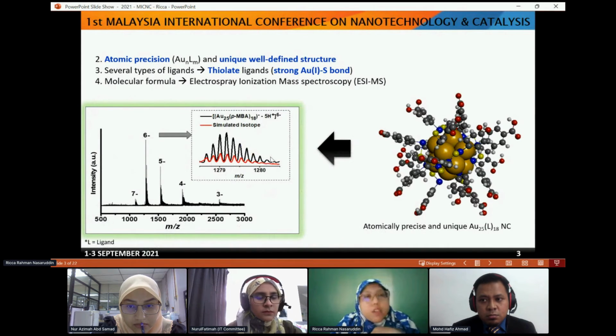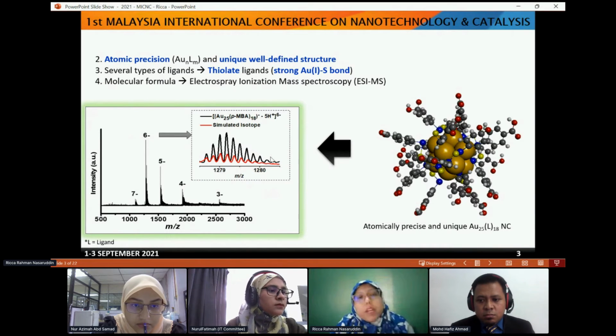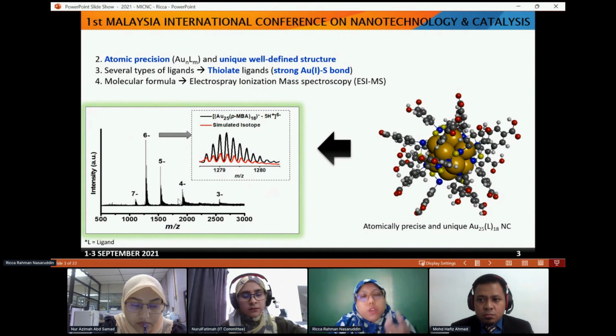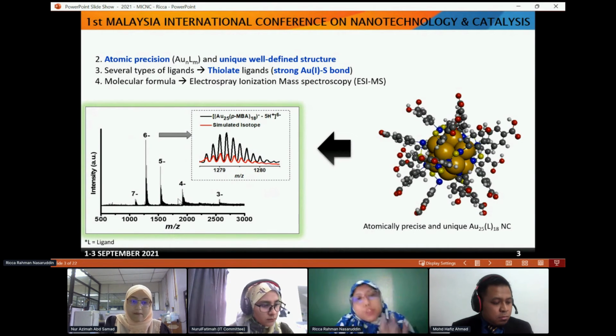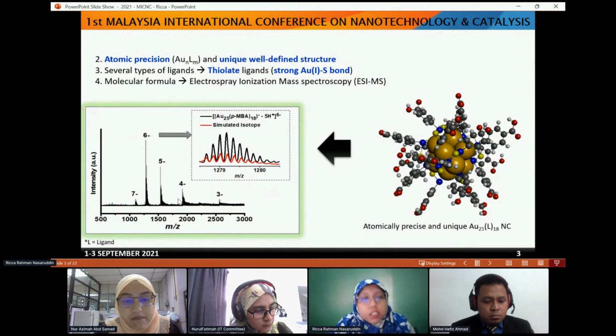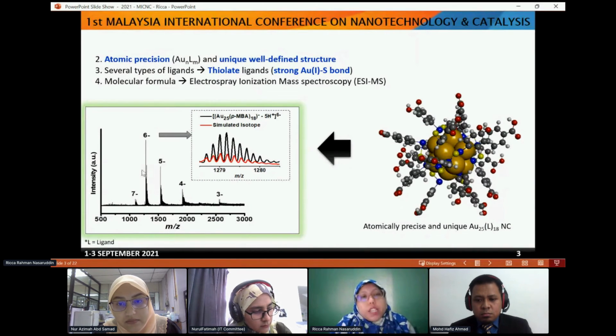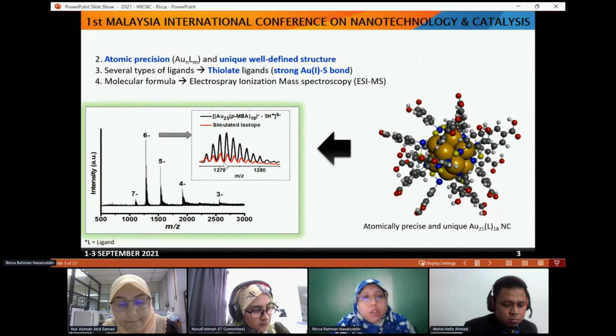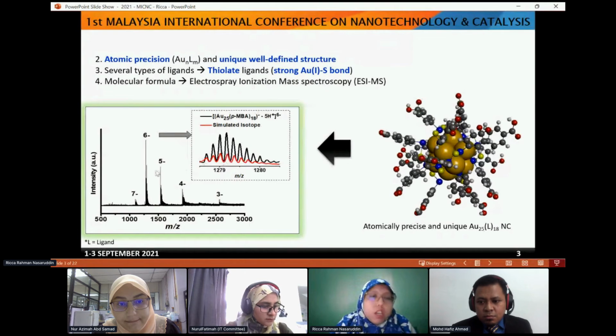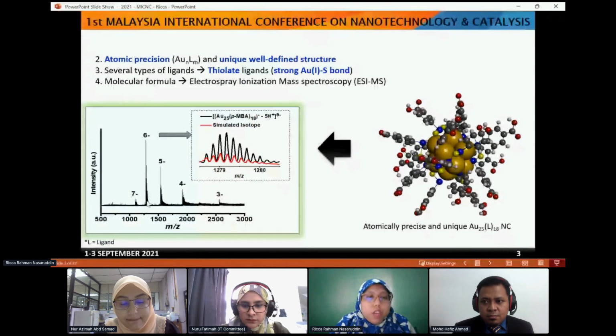And not only that, because it has this atomic precision, if you want to identify the species of your metal nanocluster, like gold nanocluster, you can do ESI-MS analysis. You can do a simulation of the isotope pattern, and you can identify the species. For example, this one is Au25, and all of these are also Au25, but this one with a 6- charge. It is well matched, so you know that your sample has high purity of Au25.